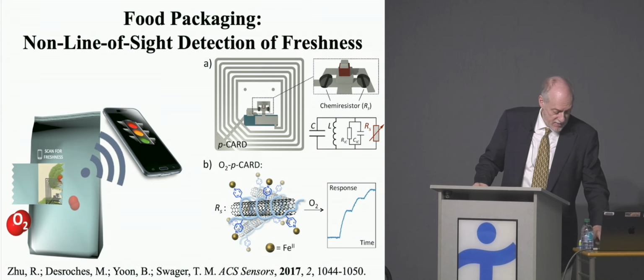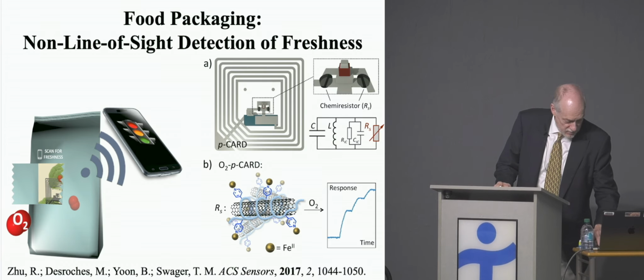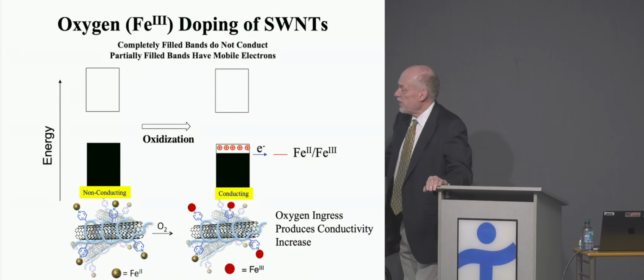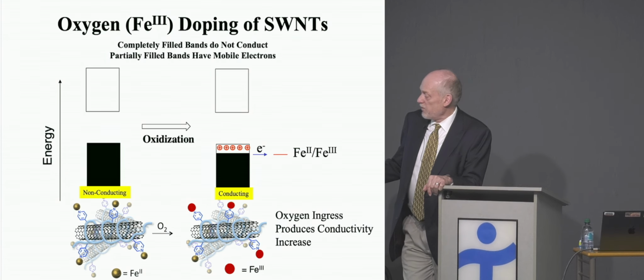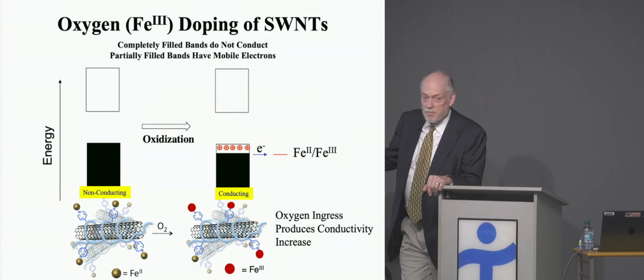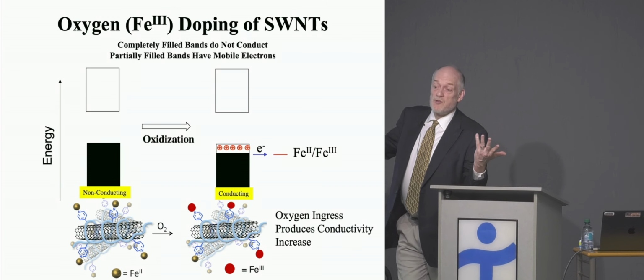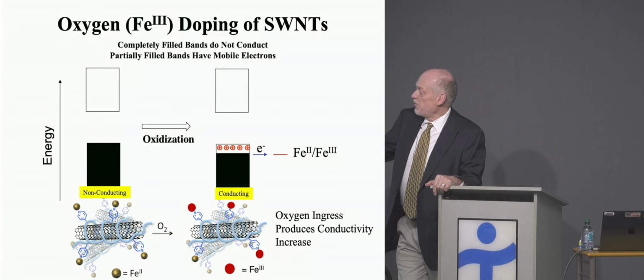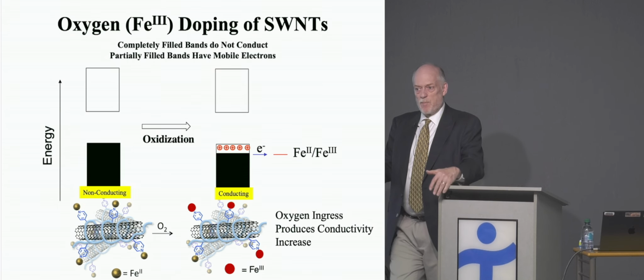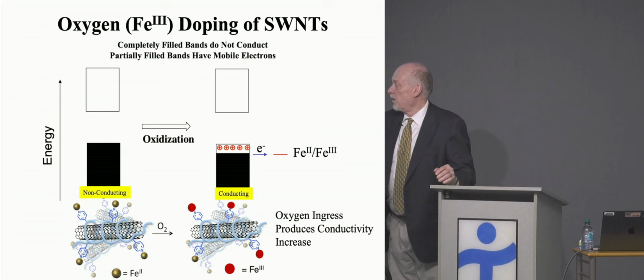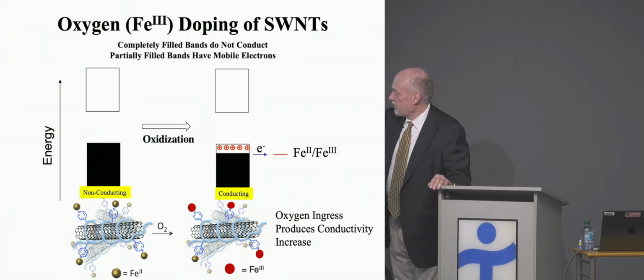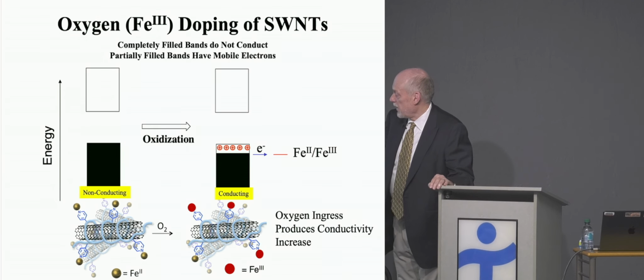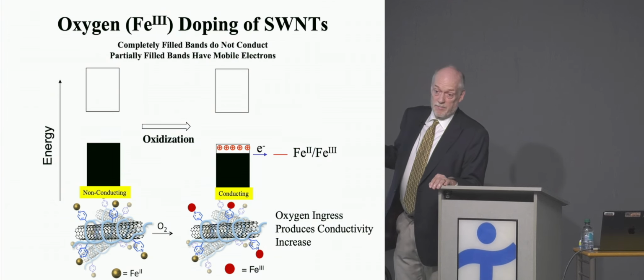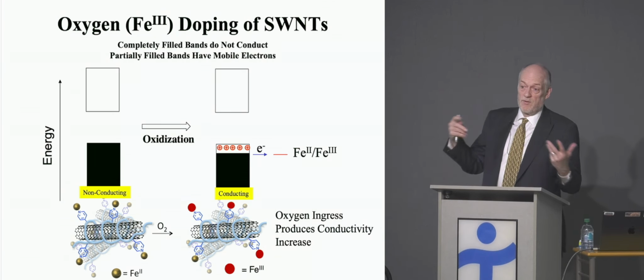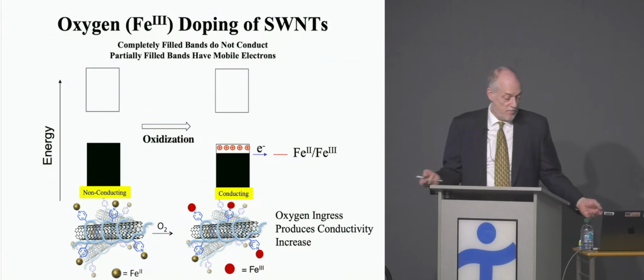So the idea here is, again, with my doping concept, that, whoops, I went backwards here. Okay, so the iron is a really good reducing agent. It's dumping electrons into this nanotube, which ordinarily would be doped or have holes in it. The iron(II) fills them up. So we assemble this all under inert atmosphere, under nitrogen, and then if any oxygen is around, it starts oxidizing the iron(II) to iron(III). We get some of these iron(III)s, and the iron(III) takes electrons out of the nanotube and creates holes, and it becomes conducting. And so this is a way that we take our nanotubes and make them really sensitive to oxygen.